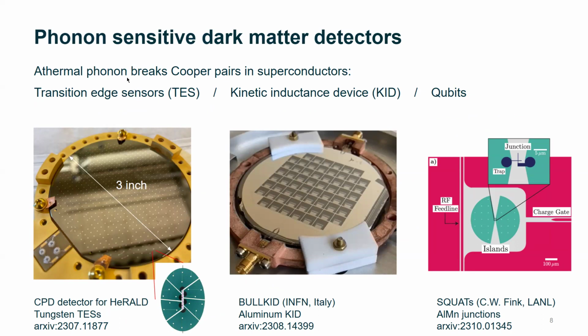We want to look for phonons, and specifically we're looking at athermal phonons, meaning the higher energy phonons that are higher than the thermal phonon distribution. And we use the fact that they break Cooper pairs in superconductors to look for them. So we look for superconducting devices. For example, the TESs. I'm from the Tesseract collaboration, and we have two detectors. One is called Herald, the other called Spice. Altogether, we call ourselves the Tesseract collaboration.